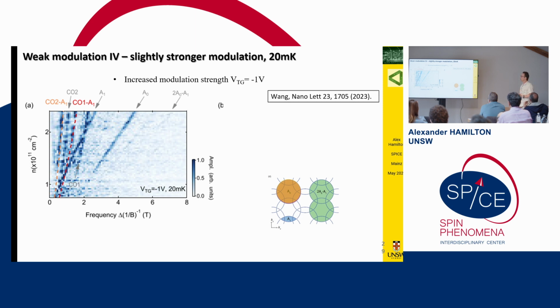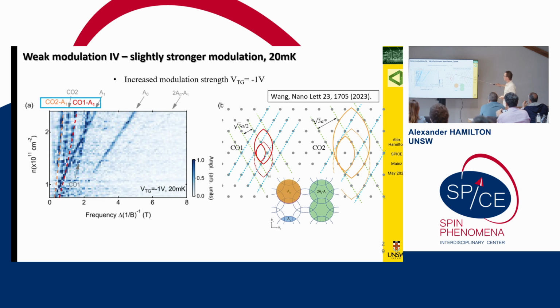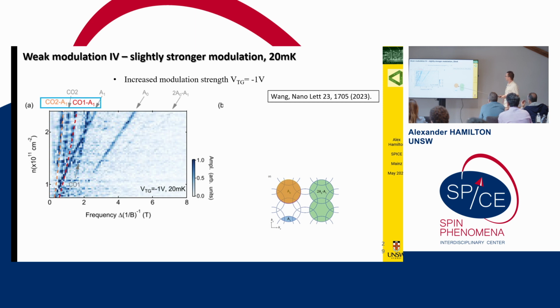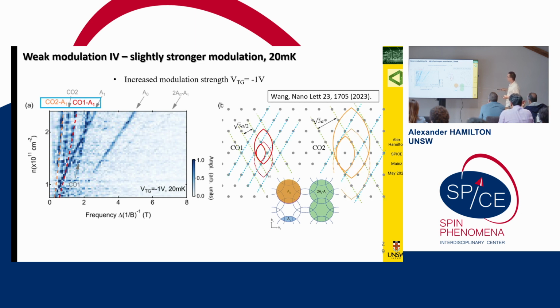If we turn up the modulation a little bit, we have these multiple different Fermi surfaces. But then we get, in addition, 2 extra frequencies in the Fourier transform. And this caused us some consternation until we realized that what those frequencies are is: here is my artificial Fermi surface, and here is my lattice. And I'm scattering my artificial Fermi surface off the periodic lattice. So I've gone from having this circular Fermi surface to having this A1 Fermi surface.